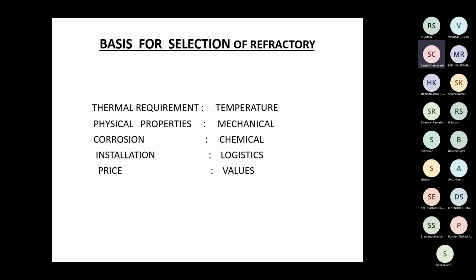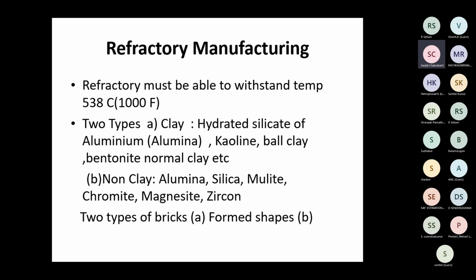It takes a huge time, and you have to lay all the lining of the plant. It can cover around 850 heats. One heat takes around 2 hours to make your pig iron into steel. This is the statistics of the steel plant. So these are the parameters. How do you select a refractory? Physical properties and so on.